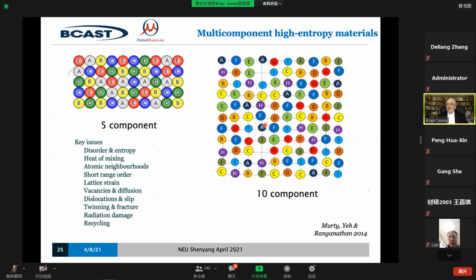And by the way, if you think about it, an atom like A is not only influenced by its near neighbors, it's sometimes influenced by its second near neighbors. If you include the second near neighbors, then it goes off the roof. It turns out that in the 5-component face-centered cubic Cantor alloy, if you include second near neighbors, and some properties depend on second near neighbors, there's about a 4 or 5% effect of second near neighbors, which is sometimes crucial. Then the number of different local clusters you can have gets to 10 to the 20 or something like that.